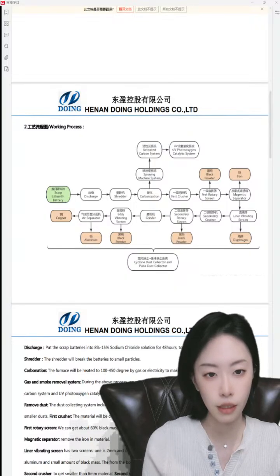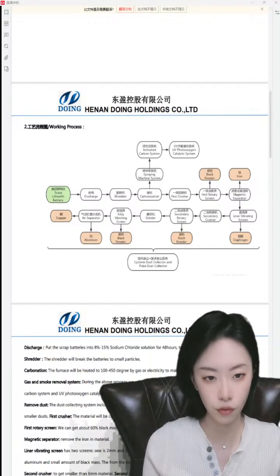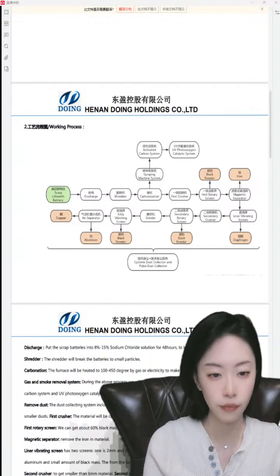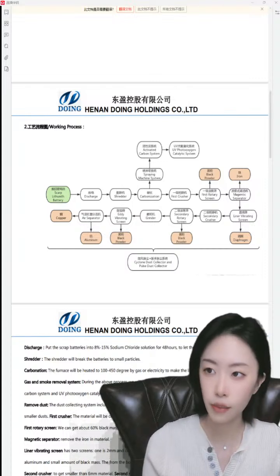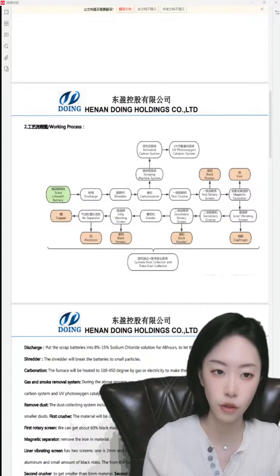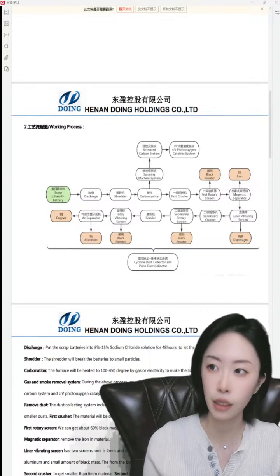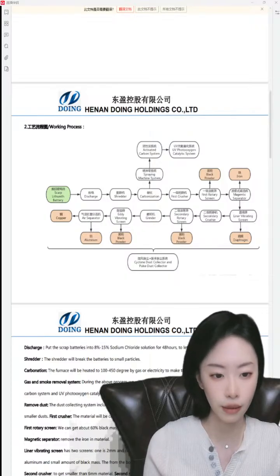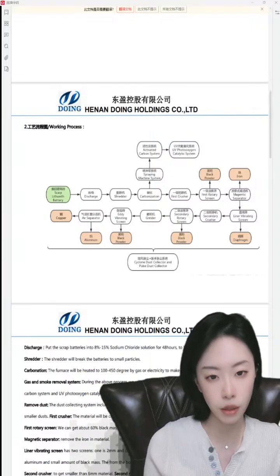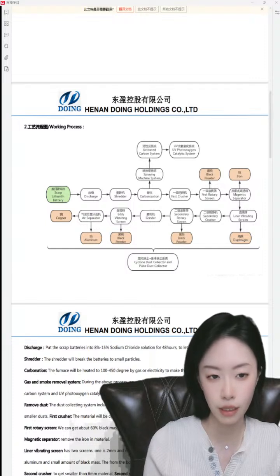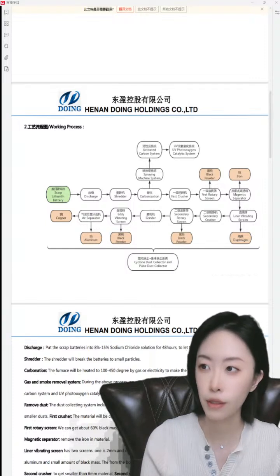After this processing step, we need to dry the materials. You can choose natural drying or use a drying machine. The drying machine is at just 100 to 200 degrees. We're using a carbonation furnace to dry them, or we call it the drying furnace. If your capacity is smaller than 50 kilograms per hour, then it's not very necessary to do this. Or if you have a huge amount of materials to process, we suggest that you have a drying machine.